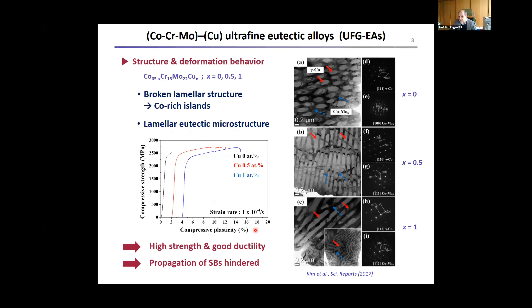This is the result in terms of strength and ductility values. If you modulate and fine-tune the composition and work with copper additions, you can see that you sacrifice something in terms of the strength level compared to the glass — reaching something like 2500 MPa — but you gain a lot of ductility. Switching from the single-phase glass to something like eutectic structures is one route to prevent catastrophic propagation of shear bands, giving you a combination of quite high strength values and good ductility.